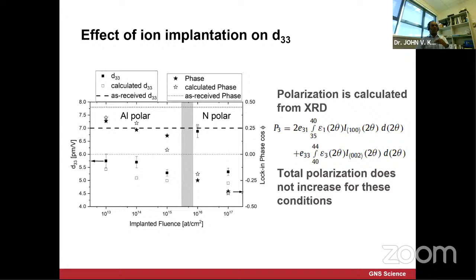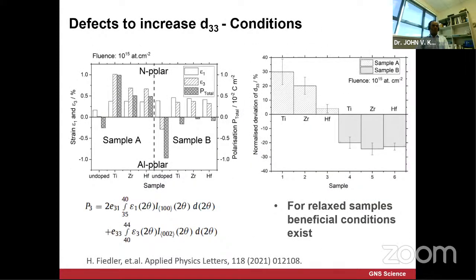Then we plotted implant fluence against d33 from the piezoelectric force microscopy. You can start to see that we can actually change it significantly due to the implantation fluence, and the calculated value and also the measured value reasonably match. This shows that additional information about the polarization, which is related to the stress gradient, can also be calculated from the XRD data. So we went on to focus a bit more deeply on many samples where we can change the strain gradient ratios and calculate the information from XRD data, then compared it with the PFM data, everything.